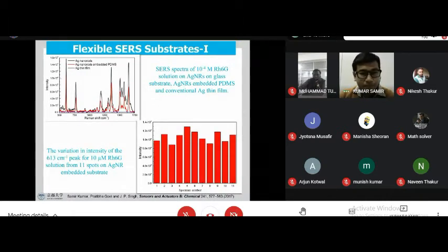So this is the Raman spectra of rhodamine-6G. It's a standard probe, 10^-4 molar rhodamine-6G. The black curve is for the silver nanorods, and the red curve is for the silver nanorods embedded inside the PDMS. And the blue curve is the thin film. So that's just for reference. We can see there is a slight loss in the intensity for the nanorods after embedding, but it's still good enough for practical purposes. So not very much loss in the enhancement factor.